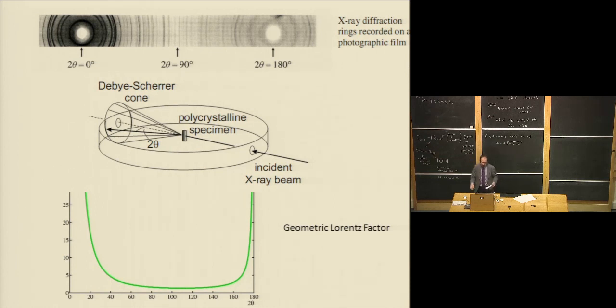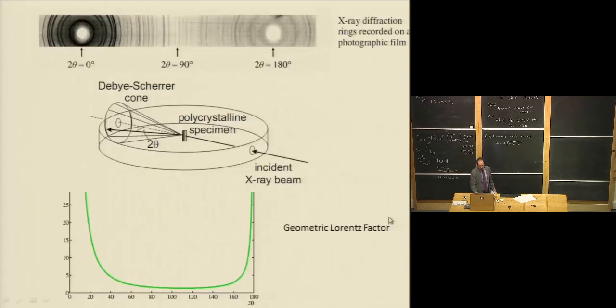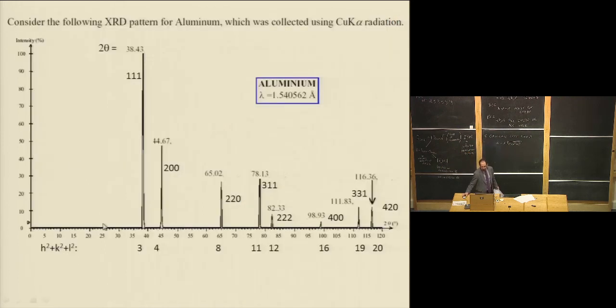And for most angles, here we're only scattering up to about 120 degrees. So this factor here is decaying as a function of angle up to 120 degrees. This factor here is also decaying as a function of angle. So we'd sort of naively guess that we should always decay as you increase the angle. And more or less, the scattering amplitude is decaying as a function of angle. But we haven't looked at this piece here, probability of alignment. Well, you might think to yourself, all the crystallites are aligned completely randomly, so that factor should be trivial. It should just be one.